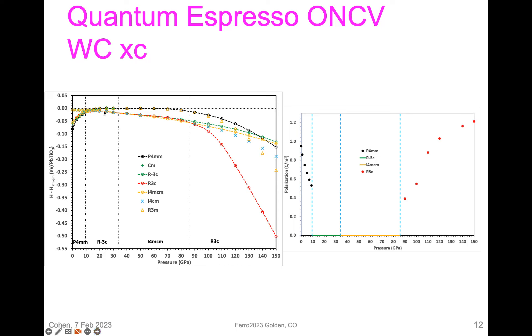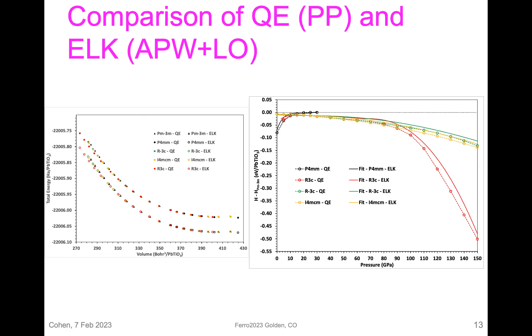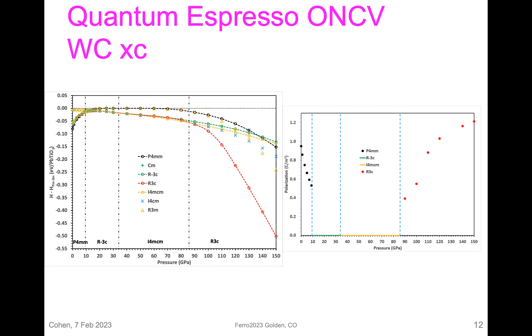In this region you can see that all these different phases are almost the same enthalpy — you need millivolt-per-atom accuracy to get the right phase. And then at about 35 GPa, we find another centrosymmetric structure, tetragonal I4/mcm. Both of these are zone-boundary instabilities — first the R-point, then the M-point dominates, and then it goes back to the R-point again. So this is a ten-atom unit cell.